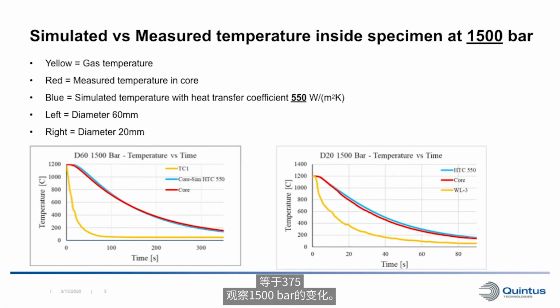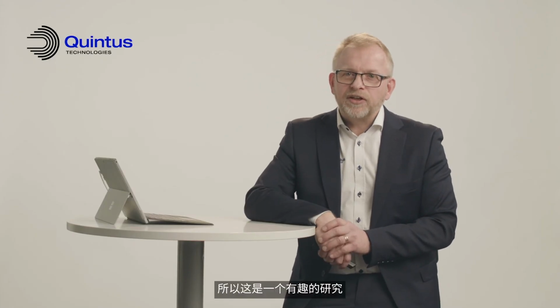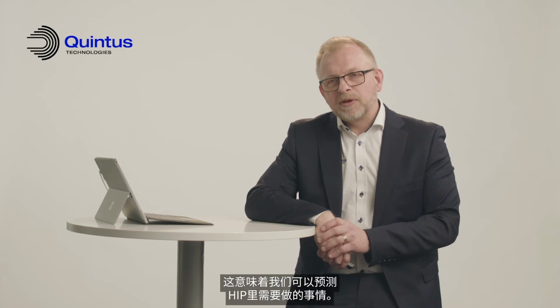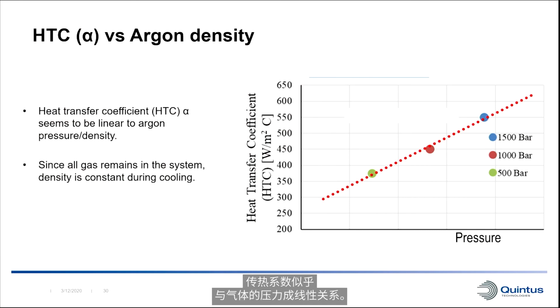And looking at 1,500 bars, things change. So we also saw that the alpha, the heat transfer coefficient, is much higher at the higher pressure. So this is an interesting learning from this work. But it means that we can actually predict what needs to be done in the HIP. But the heat transfer coefficient seems to be linearly related to the pressure of the gas.